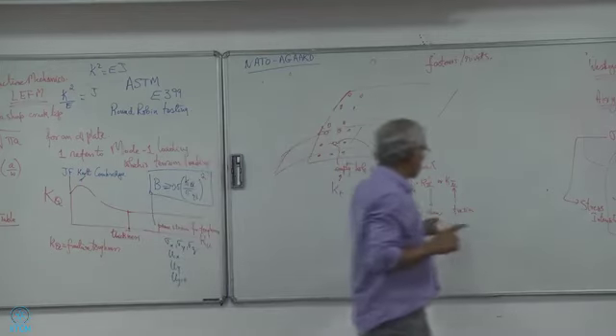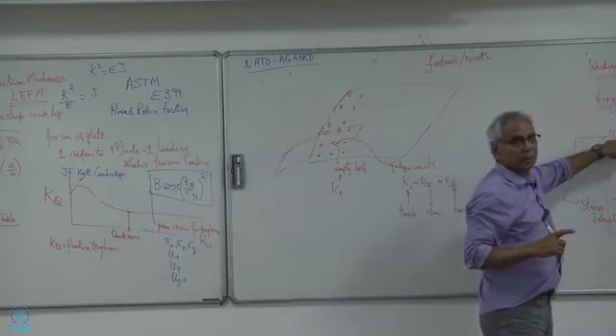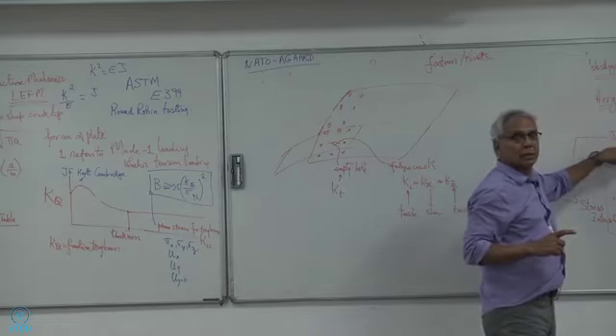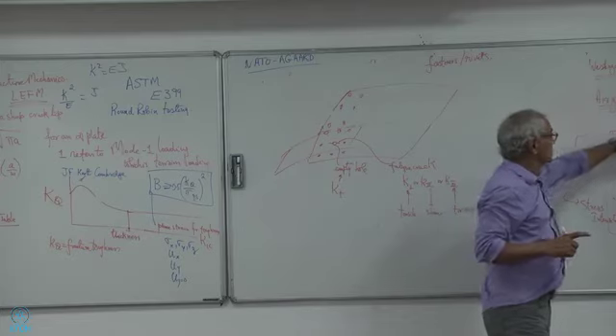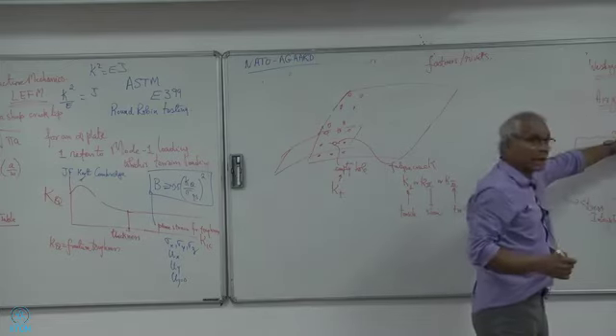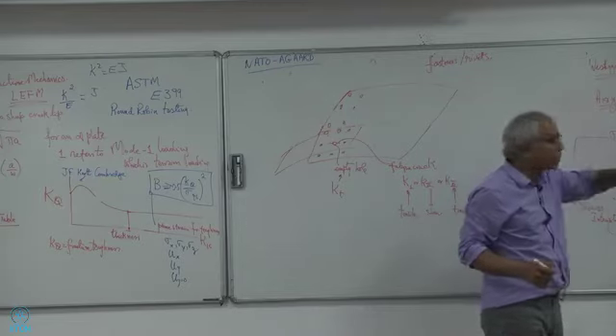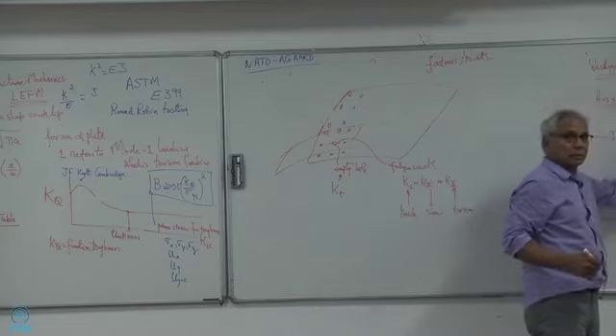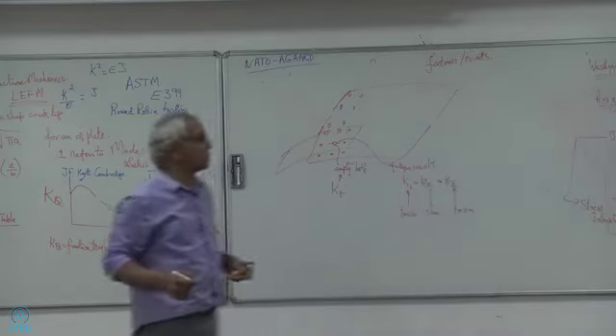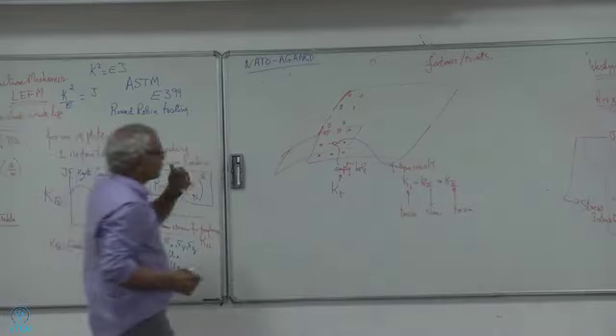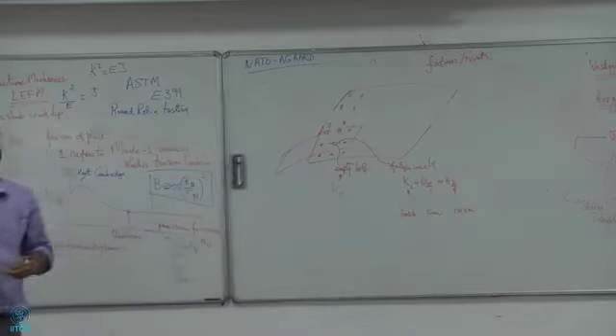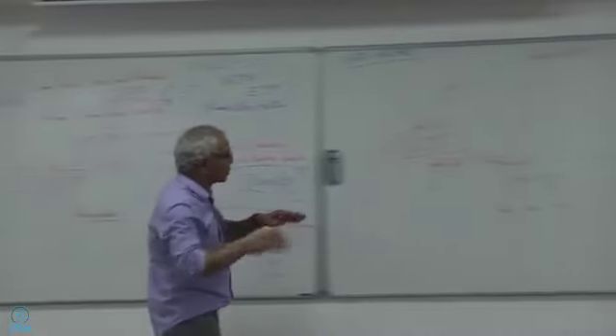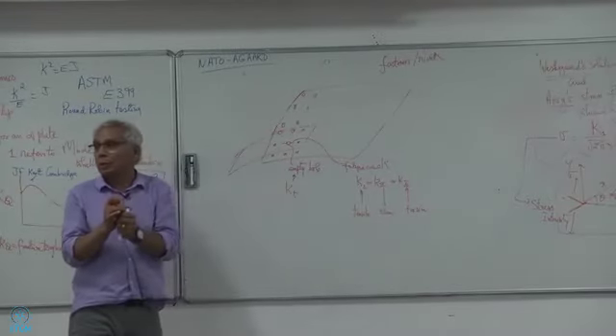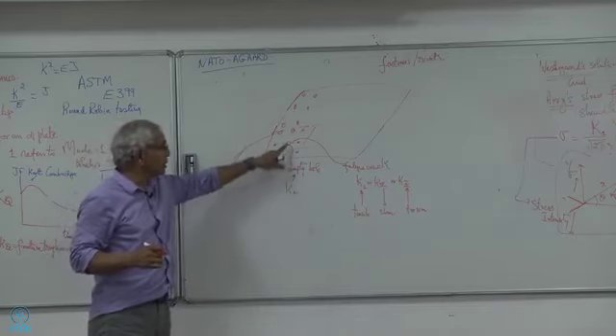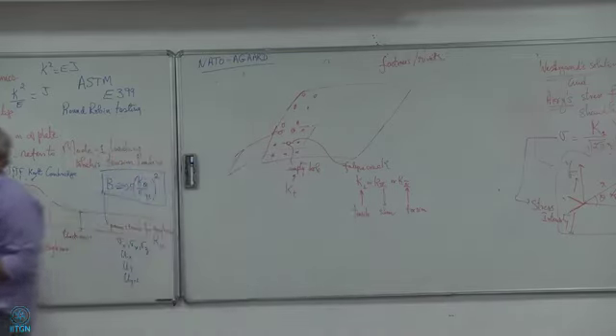So in all these cases, tensile, shear, torsion, this keeps changing. So this that I have drawn here for mode 1, this will be K1. For mode 2, this will be K2 and mode 3. Mode 3 is actually the simplest problem. It doesn't have all these complications. So, but basically that's what we do. But the point I wanted to get across for us right now, instead of getting too much into fracture mechanics, just for our work, as long as it's an empty hole, K sub T, and then once the fatigue crack comes, then you have to go to analysis of K1, K2, stress intensity analysis.